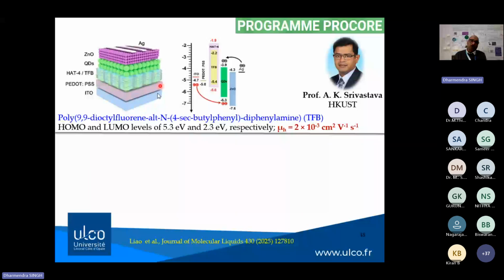So here we have done this as a joint project with the Hong Kong University of Science and Technology. TFB is the polymeric material which is used as a hole transport layer material in the LED devices, which you use commercially or at your home. One basic problem with this material is its limited hole mobility, that is 2 times 10 to the power minus 3 centimeter squared per volt per second. So we first used our pristine material as a hole transport layer material, but unfortunately it didn't work. Then we thought to mix the HAT4 material with the TFB.